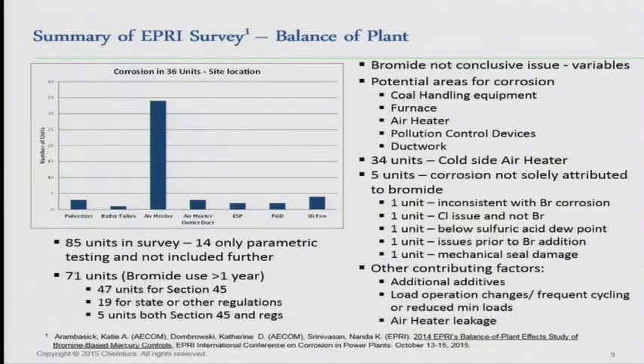And basically what they saw, as you can see in the graph there, was the cold side of the air heater was primarily where they really saw the most impact. They did have 5 units that reported corrosion, but they were kind of anomalies. One of those units, the corrosion didn't start on the outside and work its way in, so it wasn't totally conclusive that the bromide was causing that. It could have been another issue.